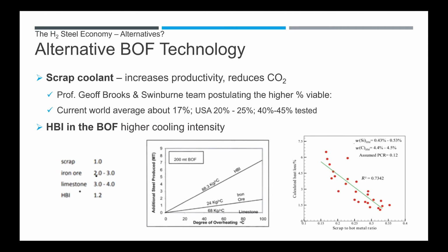I'm sure the team at Swinburne that talked this morning looked at the scrap coolant to increase productivity and reduce CO2. Currently in the world, it's 17%, and in the US, it's between 20 and 25%, and 40 to 45% has been tested. And Swinburne believe strongly that it can be up to 40% quite easily. The other issue is adding HBI in the BOF, which has a higher cooling intensity. It's about 20% better than that of scrap. Next, please.